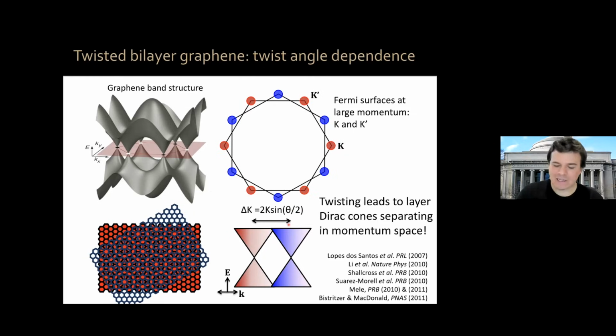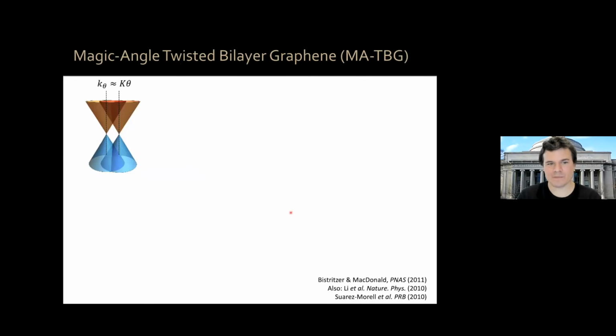Now, let's start from a small rotation angle so that this sine is already equal to the angle, and let's see what happens to the electronic structure. So if we start from a small rotation angle, the separation between these 2 Dirac points is proportional to the angle. Now, this would be the electronic structure if the electrons in one graphene sheet didn't know that the other graphene sheet exists. However, when we place graphene on top of graphene, these two sheets are just 3 angstroms apart. Okay? So electrons are very much aware that the other graphene sheet exists, and in particular, they can tunnel